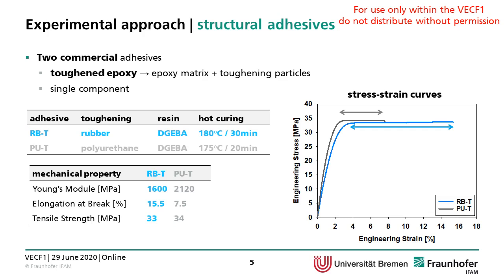Here on the right side, you can see the different stress strain curves of both adhesives. So the PUT adhesive is slightly more stiff, so has a Young's modulus of 2000, and the RBT has a Young's modulus of 1600. The RBT adhesive is much more plastically deformable, so with an elongation at break of 15.5 versus 7.5 of the PUT adhesive. And they have quite similar tensile strength, so around 33-34 megapascal.